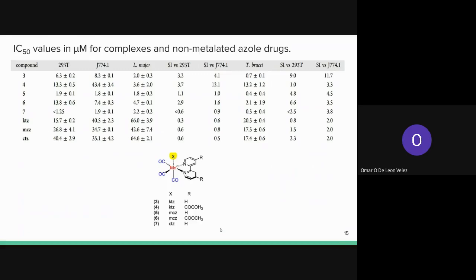For Trypanosoma brucei, they found different results. The non-metallated compounds were also less potent than the metallated compounds. Most of them also had issues with selectivity, with the exception of the first compound, which is ketoconazole without the methyl ester substitution. This one actually had the highest selectivity index in both mammalian cell lines, indicating that it has a considerably higher selectivity. So basically, the authors established that this compound is the most promising one, and that it should be studied further.